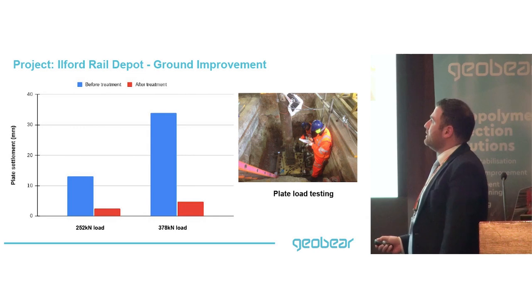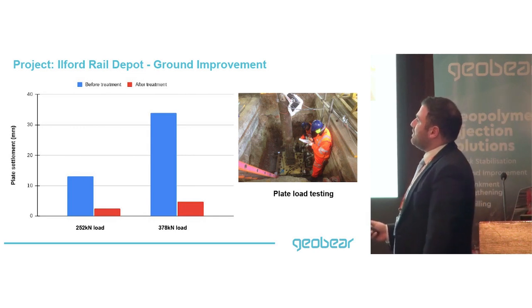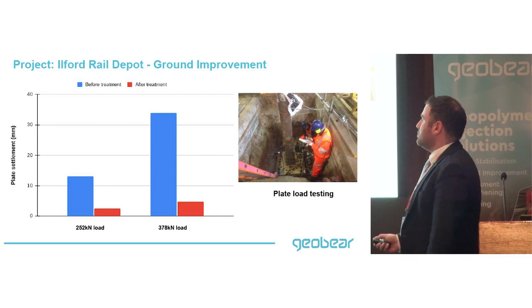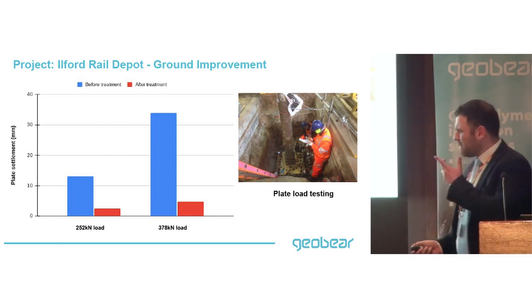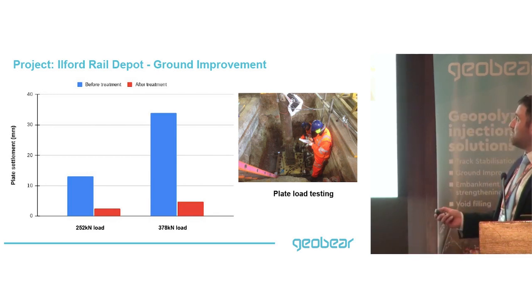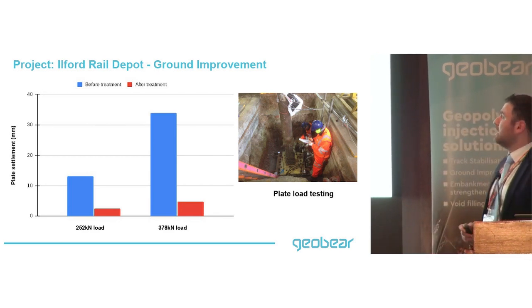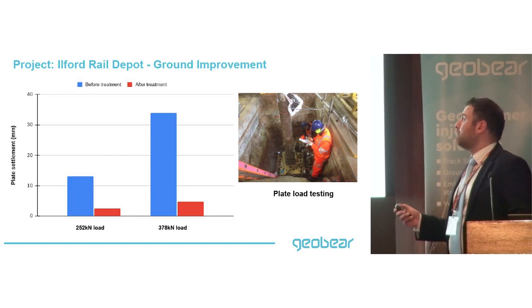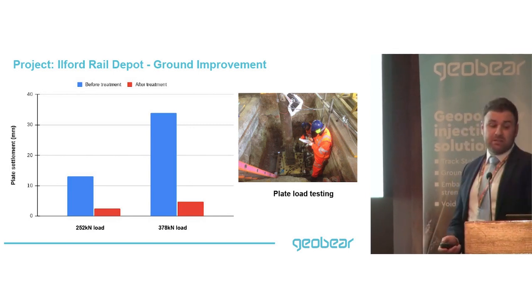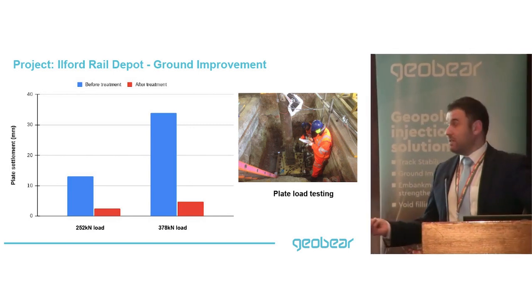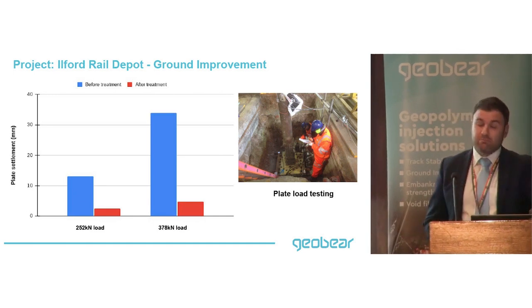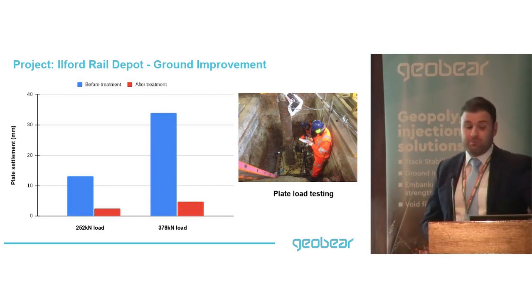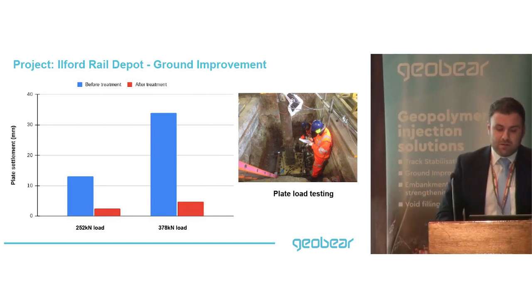On the high loading, the deformation was around 34 millimeters, and that was brought down to about 5 or 6 millimeters. So quite a substantial improvement in the bearing capacity or resistance to deformation. Quite a success, and probably what we've done, we've overdone it in this case, and we've overachieved the design targets.